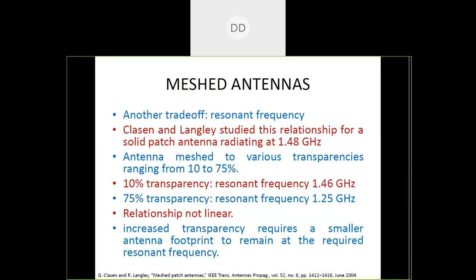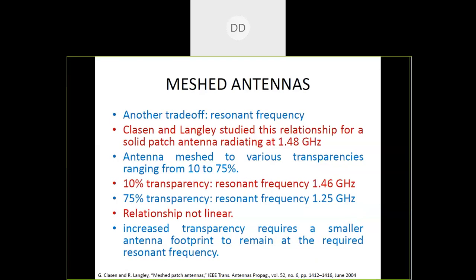Then another trade-off for these meshed antennas is resonant frequency. Studies have been conducted to analyze the effect of transparency on the resonant frequencies. In one study, Clasen and Langley studied this relationship for a solid patch antenna radiating at 1.48 gigahertz. They meshed the antenna to various transparencies between 10 and 75%. They observed that at 10% transparency, the resonant frequency of the antenna was 1.46 as compared to 1.48 for the solid antenna. As they increased the transparency, the antenna frequency decreased. 1.25 gigahertz was observed for 75% transparency.